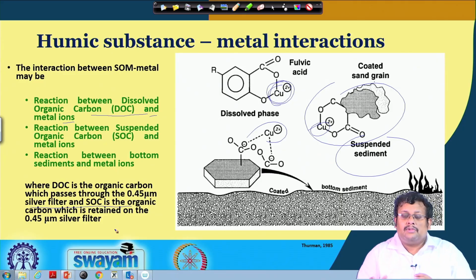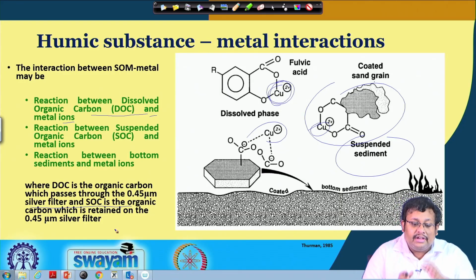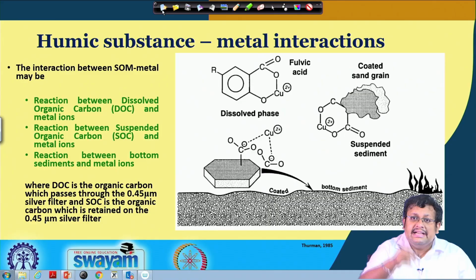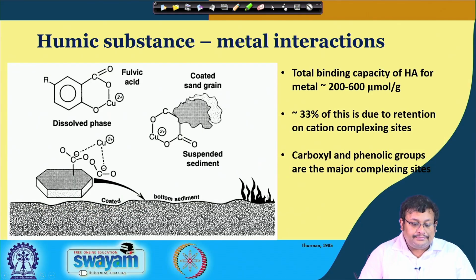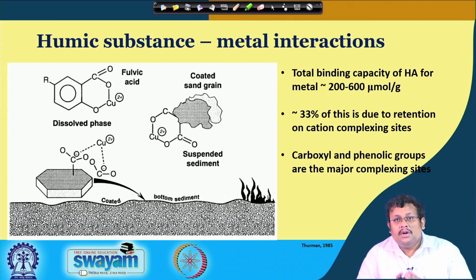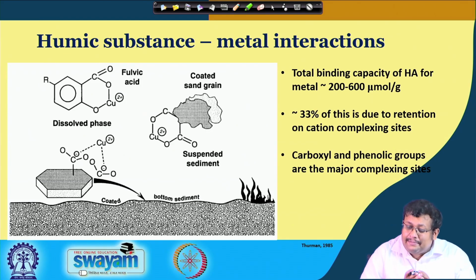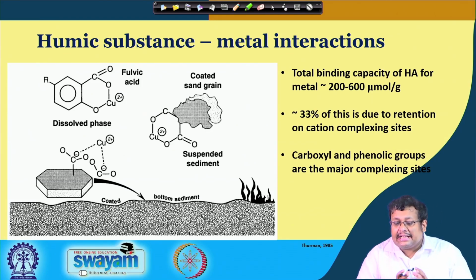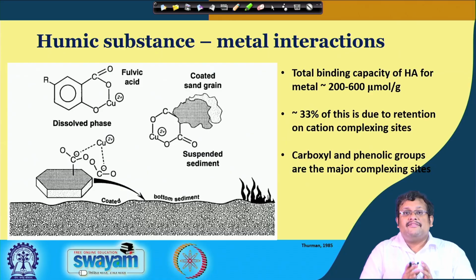So, in case of a water body, we can see these different types of humic substance and metal interaction in three different phases. The total binding capacity of humic acid for metal varies from 200 to 600 micromole per gram, of which 33% is due to retention at cation complexing sites, and carboxyl and phenolic groups are the major complexing sites.